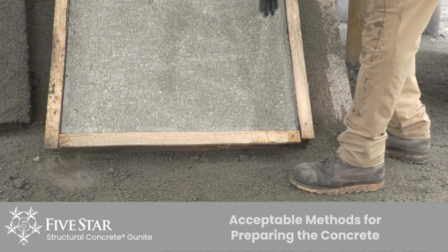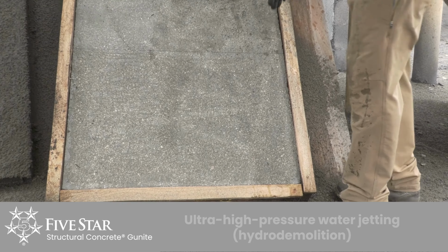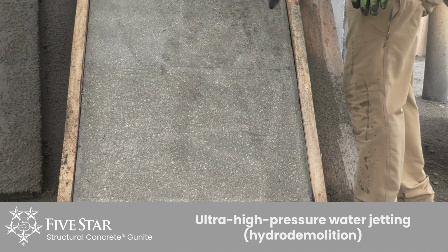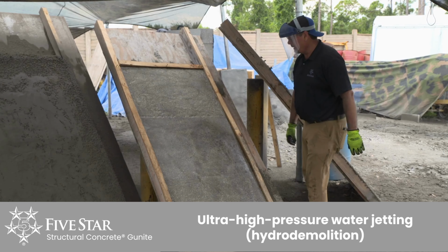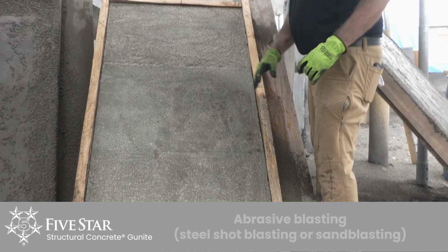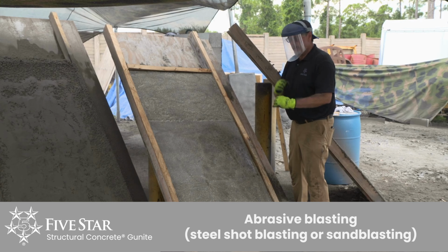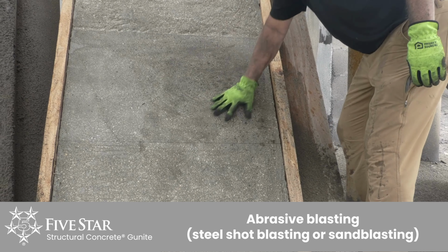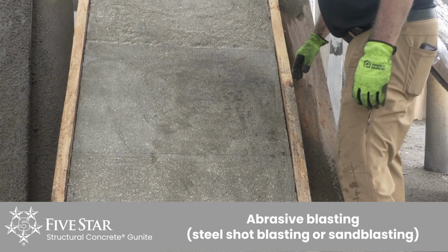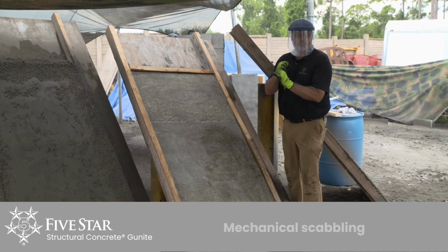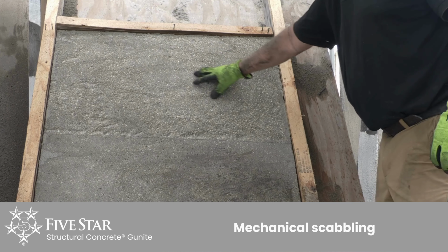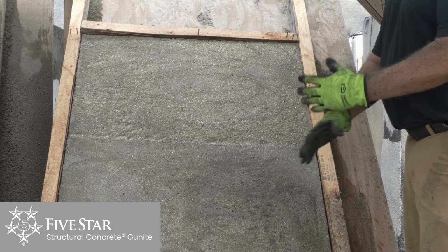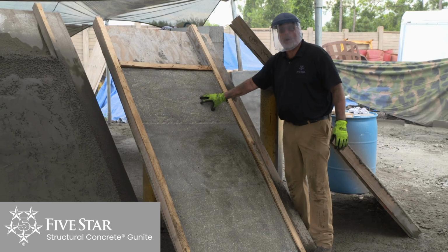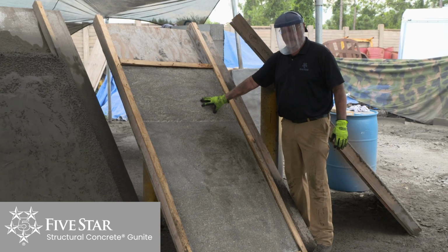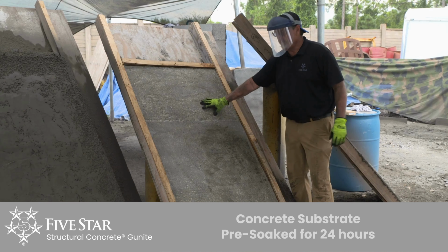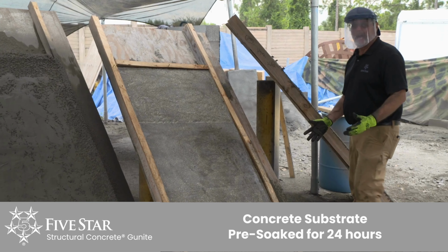At the very bottom, we've used a highest pressure water blast to take off the top creamy layer of the concrete to expose aggregate. In the middle section, we used a shot blaster, basically a sand sprayer, where we've exposed aggregate with that as well. At the very top, we've used a mechanical scabbler. It basically dimples the surface. In each one, we've taken away the laitance layer to give something good to bond to. We want to see exposed aggregate. This material has been pre-soaked for about 24 hours, so it's ready for the application.